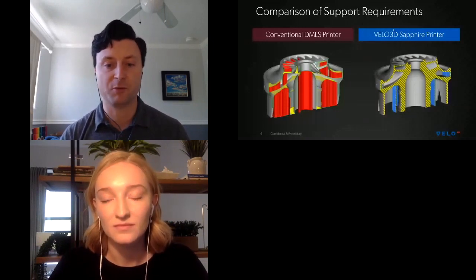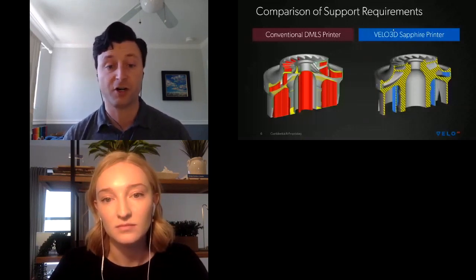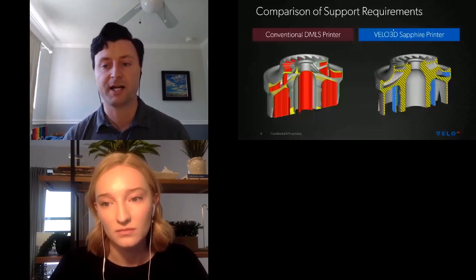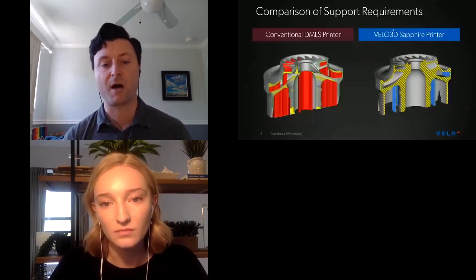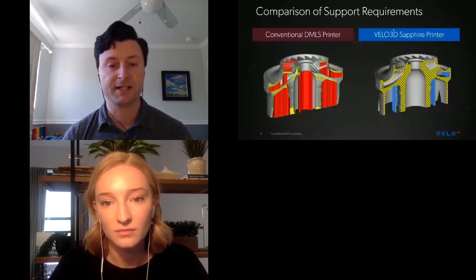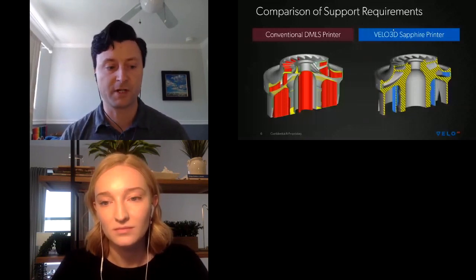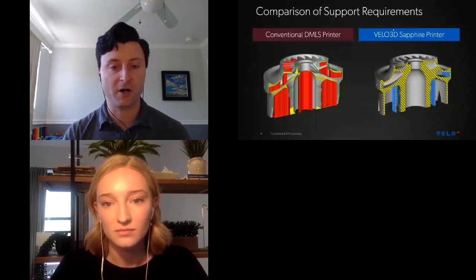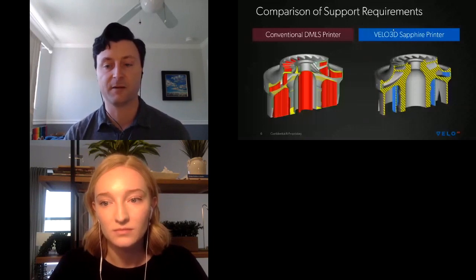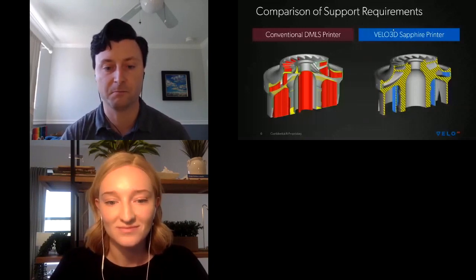Regarding melt pool monitoring, we absolutely have melt pool monitoring, and I think the more important thing than just the monitoring is that our Assure quality assurance software is actually interpreting that data and giving the user actionable feedback around defect detection, both in terms of the porosity of the part, so the probability of pores being formed in the core material, and then also from surface roughness. And so like in a manifold, when you have internal diameters that are very hard to scope or CT, depending on the material, our system actually can show if there are surface defects that are caused by, as an example, a melt pool instability. So those are two very powerful metrologies that come with the Sapphire system.